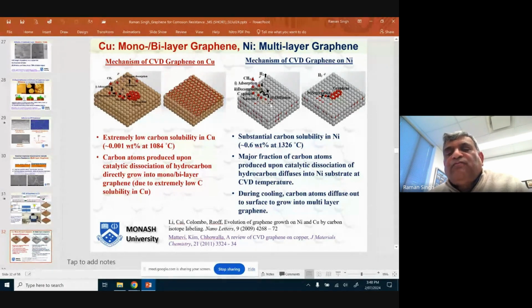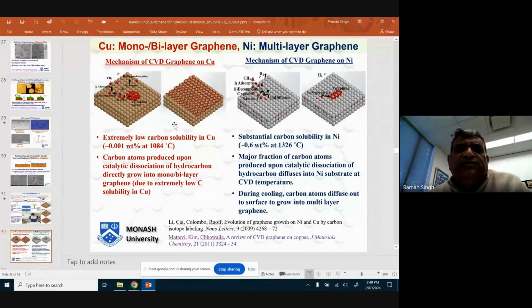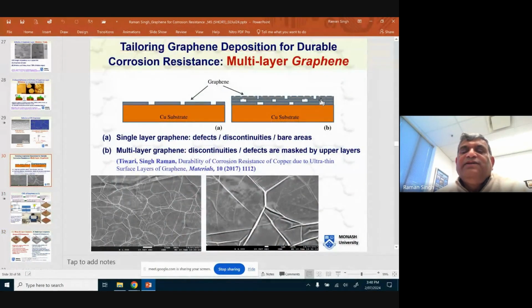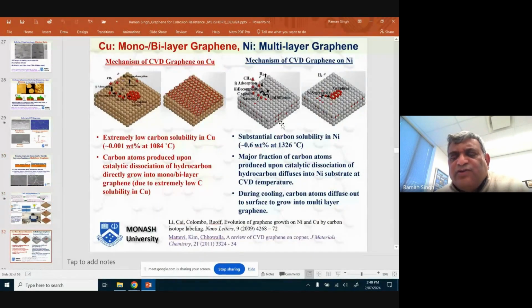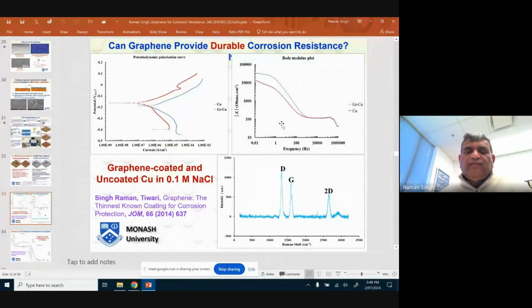And because of this difference in mechanism, it is difficult to form more than one or two layers on copper, but you can form multi-layer graphene on nickel. And if you remember, our interest was to develop multi-layer graphene. So from here onwards, we started to work more on nickel because it is nickel which has the ability to develop multi-layer graphene.